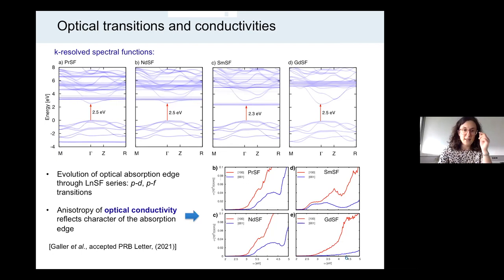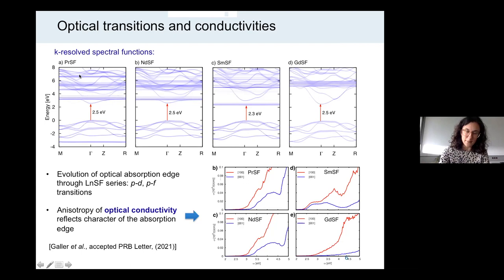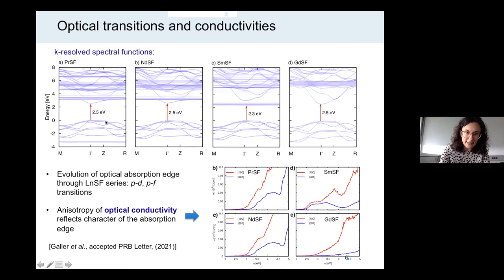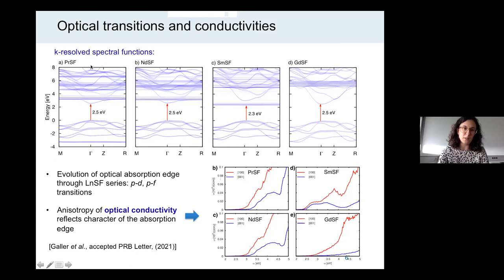The very flat bands visible everywhere are the rare earth 4f states. The not-so-flat bands in the conduction band, especially a single band coming down, are rare earth 5d states. The bands in the upper valence band are the sulfur 3p states. So the optical transitions at the absorption edge are from the sulfur p states to this rare earth d band, which strongly hybridizes with the rare earth f states — this is for praseodymium fluorosulfide.